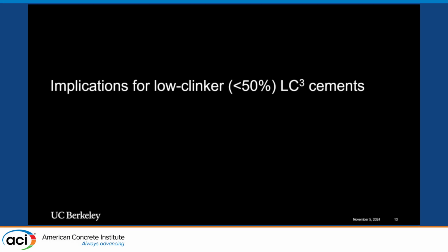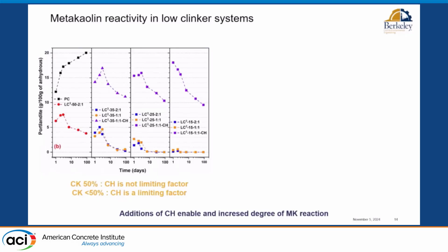So what are the implications of this carboaluminate precipitation for the horizons of LC3? For example, if we try to go below 50% clinker factor. So the problem with going below 50% clinker factor is that you have to remember that calcined clays are very reactive, but they are still pozzolans. So if you mix calcined clay with water, you get mud, an expensive one.